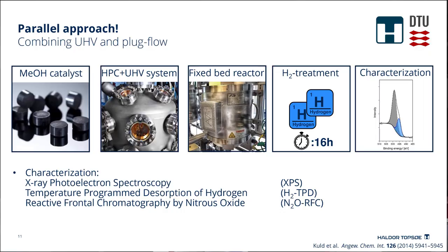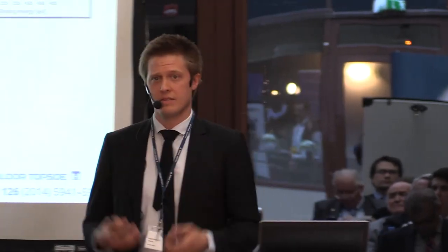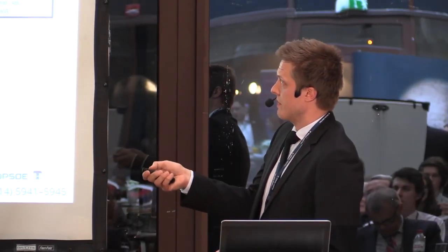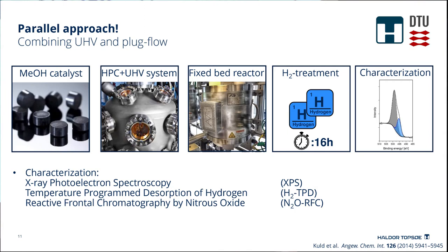So what did we do? We took a quite unique approach here, so we combined some classical ultra-high vacuum science, surface science, with the ability to quantify a larger amount of catalyst in fixed bed reactors. So we could take the industrial type methanol catalyst, we could load it into a combined ultra-high vacuum system, which has a high pressure cell attached, and we could load it in a fixed bed reactor at Haldor Topsoe. Then we could subject the system to identical treatments in hydrogen, and then we could do some different characterizations afterwards.